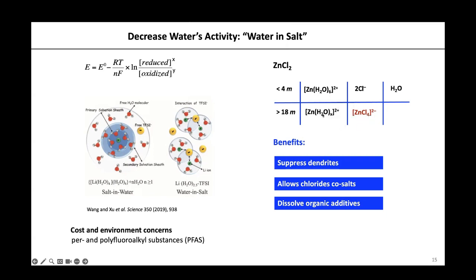Now, if you have these two ions, it turns out that the lattice energy of this new salt, if you pack them, is going to be lower. So this is a more soluble salt per se, so you can dissolve a lot of it, right? When you have a high concentration, we talked about it already, it's going to suppress dendrites. And then another interesting phenomenon is you can add other chlorides. You can add lithium chloride, sodium chloride, potassium chloride, ammonium chloride, all kinds of chloride into this electrolyte. And these co-salts will be allowed to dissolve. Why? Because the chloride anions will be used to convert more zinc ions to this anion species. And so that allows a lot of co-salt to be dissolved at a high concentration. That's quite interesting. And the third one is very important. The third one is probably the most important point here.